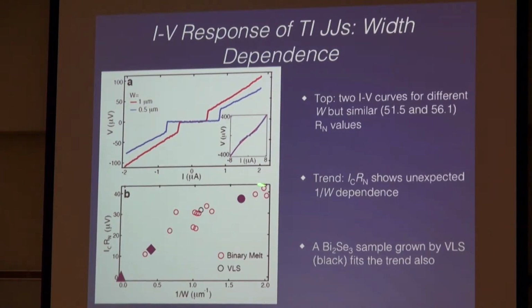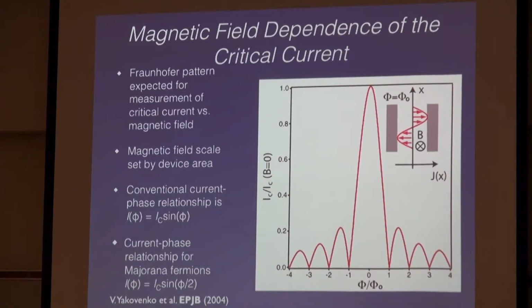And even if you go out and take data from other people's work on these junctions that have come since then, these 3 different works here, you can see that when you use bismuth selenide or bismuth telluride, you see this sort of overall 1/W trend. I don't know what to say about this. They made a device and didn't observe superconductivity. It was a very wide device, but I don't know that you should necessarily include that in the plot. Okay, so we noticed that sort of geometry dependence to this ICRN product. That was one interesting thing we saw.